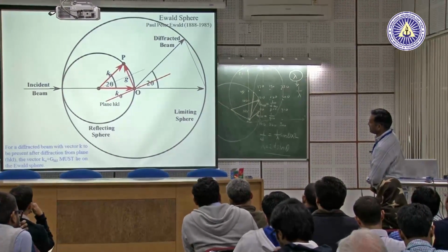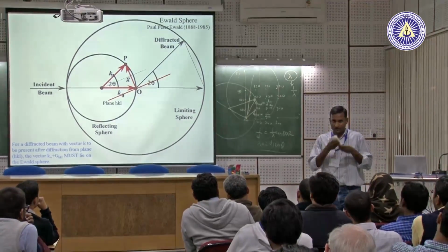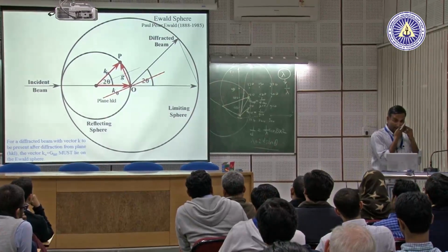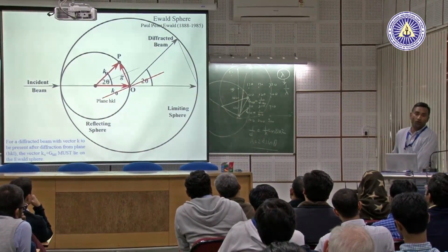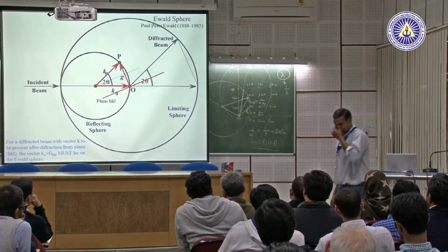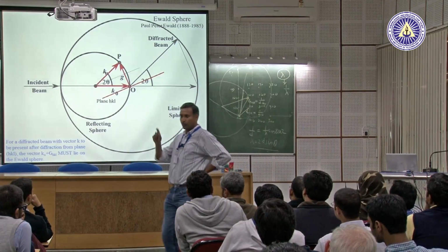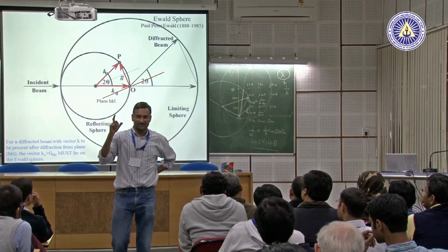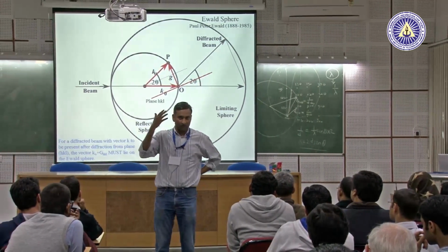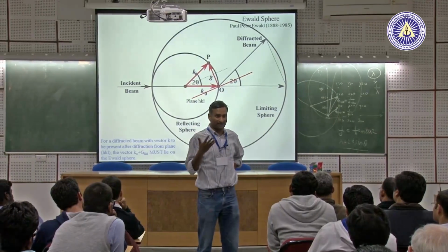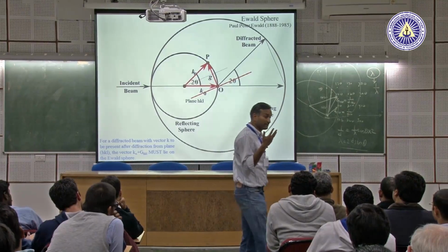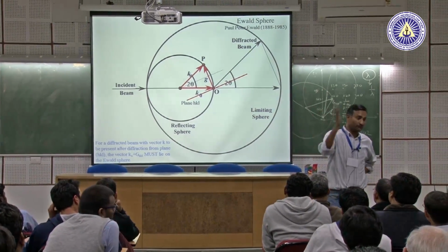The advantage is that you can now choose the direction of a beam with respect to the orientation of a crystal, and make any point diffract or not diffract. Basically it is very useful for single crystal diffraction. If you really want to find out the exact d spacing of any crystal, you collect the diffraction data for each of the points separately by changing the orientation of the beam.